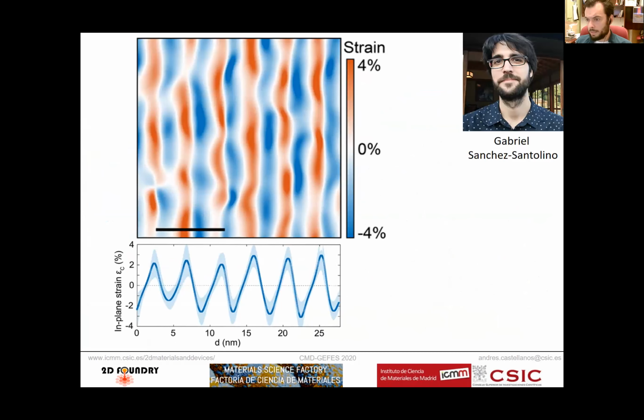I would totally think of this periodic strain as a novel superlattice. It will be a twofold superlattice in this case, because we have the structural superlattice and the strain superlattice in plane. I totally agree. I haven't thought of it. I mean, the period is around 4 nanometers, right? A little bit more than 4 nanometers. I haven't thought of any application of this lattice yet, so I will give it some thought.